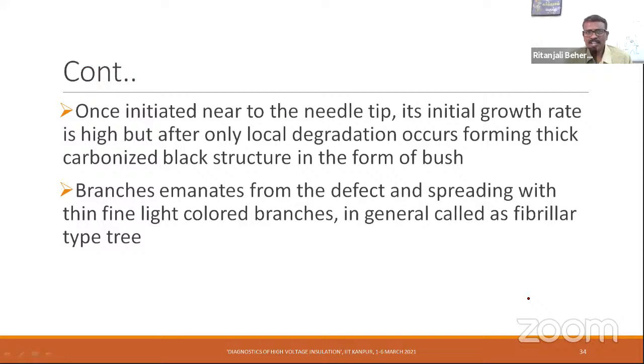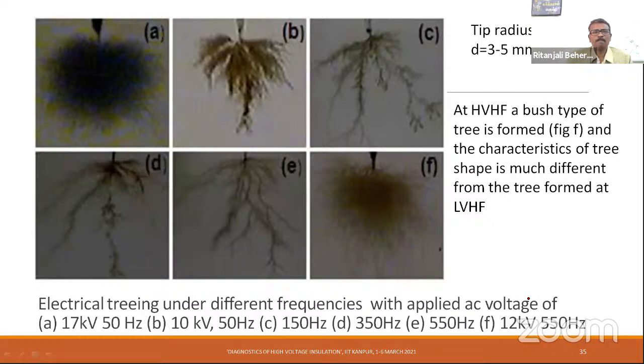Once the tree is initiated near the needle tip, its initial growth rate is high because of the presence of the harmonics. But after that only local degradation occurs, and it forms a thick carbonized black structure. That's why we'll be seeing it. In this picture, you can see that the first one, A, is 17 kV 50 Hz. That's completely a bushy tree. This is the B one, which has 10 kV 50 Hz. The only difference is the voltage. So when the voltage is reduced, with the frequency the same, it changes to more of a branchy, bush-branch kind of structure.